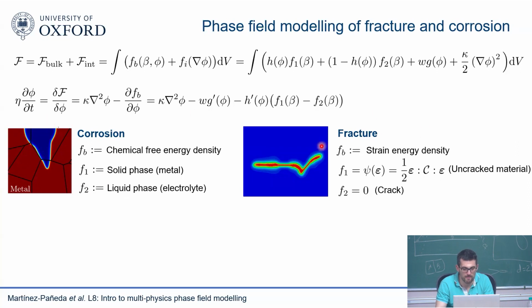In fracture, the bulk energy is the strain energy density. In phase 1, that is the uncracked material, that corresponds to the strain energy density. And in phase 2, it corresponds with the crack. It's 0. In the crack, we carry no load, so the strain energy density in the crack is 0. So this is the idea. It's the same approach. We interpolate between two quantities, but in fracture, the two phases are the crack phase, where they have no strain energy density, and the uncracked phase, where you have the strain energy density.